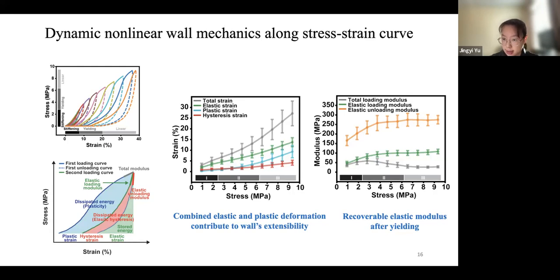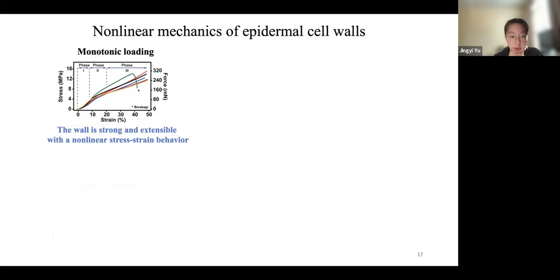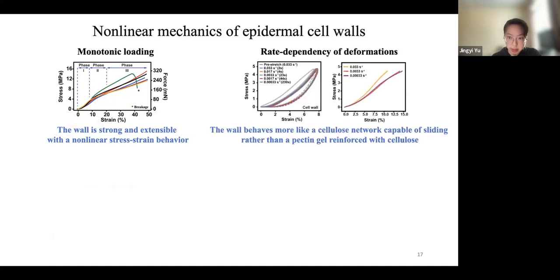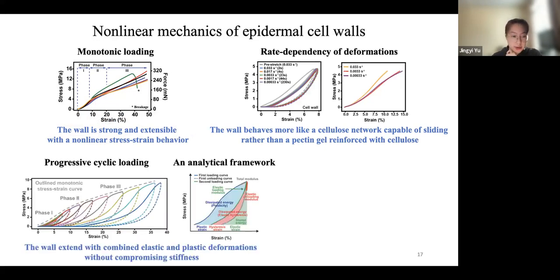And what's more interesting is that, starting from phase 2, the wall starts to deform plastically. However, this doesn't really result in a decrease in the overall elastic modulus of the wall. The wall is still able to maintain its maximum elastic loading as well as unloading modulus even after extensive plastic deformation, showing that the wall is not experiencing a significant loss of load-bearing components, and it is able to recover its elastic modulus even after extensive loading. So to summarize this part, from the monotonic loading, we can see that the wall is strong, extensible, with a very nonlinear stress-strain behavior. Following that, we characterized its rate dependency and found that the wall behaves more like a cellulose network capable of sliding rather than a pectin gel reinforced with cellulose. And finally, with the framework of progressive cyclic loading and analysis, we're able to show that the wall extends with this combined elastic and plastic deformation without compromising its stiffness.